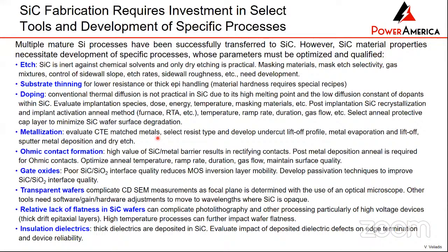Thermal diffusion, which is possible in silicon, does not apply. Metallization: the coefficient of thermal expansion of silicon carbide is different than that of silicon. So when you make a silicon carbide device, you have to select metals that have close thermal expansion coefficients in order for the device to operate at high temperatures without being destroyed. When it comes to the ohmic contact, in silicon, if you deposit a metal, you can get a good ohmic contact. In silicon carbide, because of the high band gap, you don't get an ohmic contact when you deposit metal. You get a Schottky contact, and you have to come up with a process to make a low resistivity ohmic contact. In the case of silicon carbide MOSFETs, you have a gate oxide, and it's important for that gate oxide to be clean so you can have high mobility and eliminate instability.